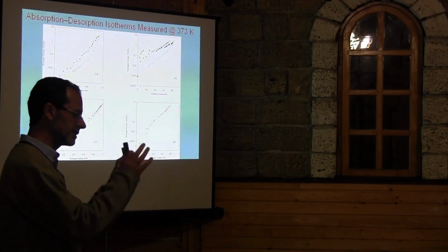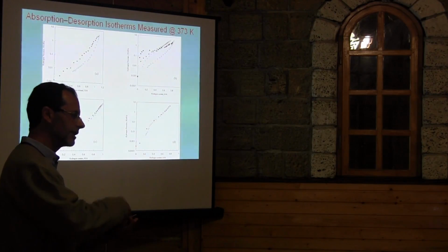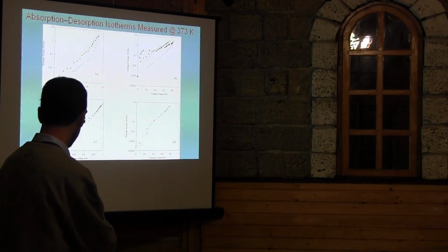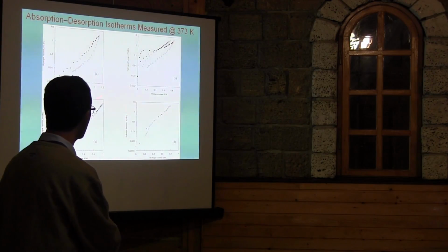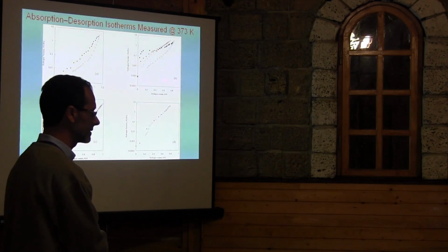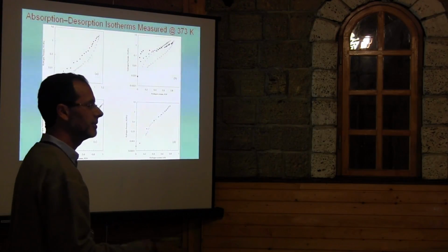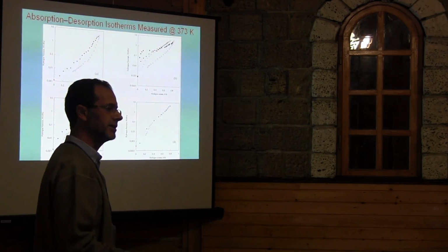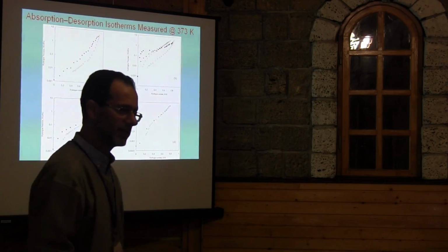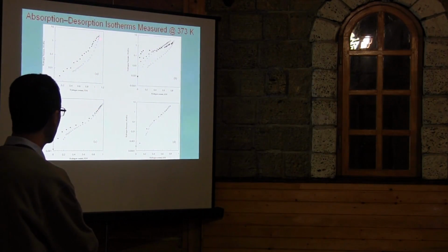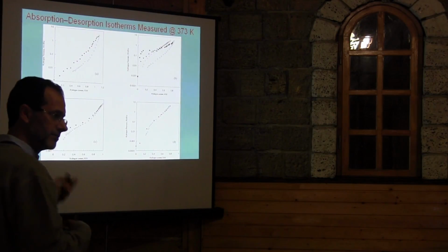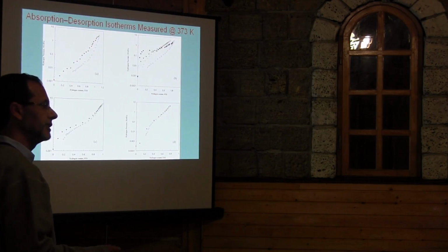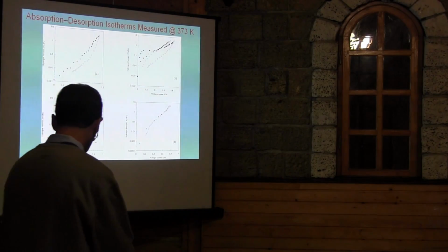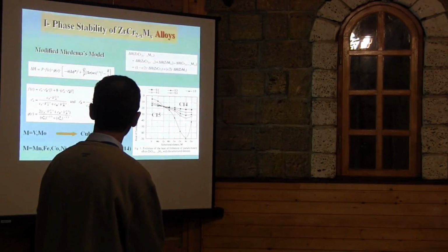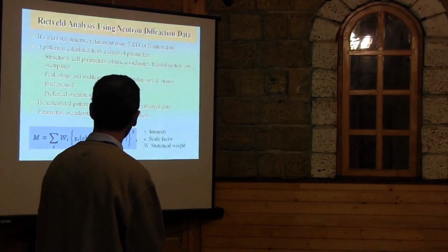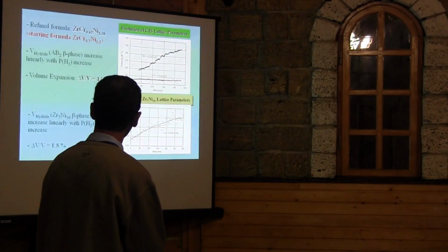So what does it mean? If you have a system, you introduce hydrogen, so you increase the hydrogen pressure, and this is the amount of hydrogen absorbed per metal. From this we can calculate the hydrogen capacity or electrochemical capacity. I will show you an example. If I have one hydrogen atom per metal, for my system, I can expect about 350, if I'm not wrong, something like this. The hydrogen capacity for batteries, just to go quickly.